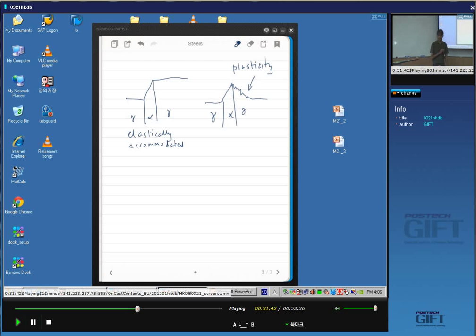And this has a very major consequence on the structure of bainite. You remember we said that the transformation interface has to be glissile. That means the dislocations in the interface must be able to move without diffusion. If you put obstacles in the way of those dislocations, then the interface cannot move. Those obstacles can be precipitates, they can be dislocation tangles, and so on. So the plate of bainite simply stops growing, even though it has not hit anything else. When this plastic accommodation builds up sufficiently, the plate of bainite which is growing simply stops growing.